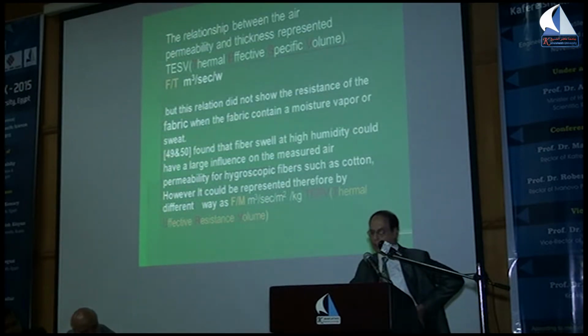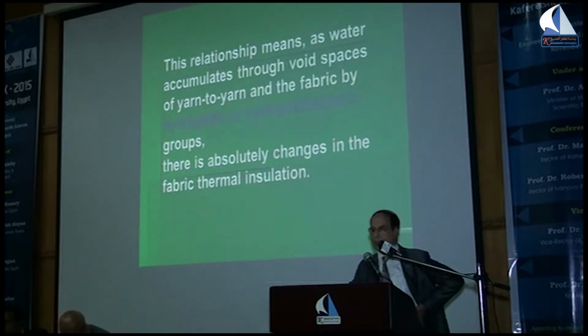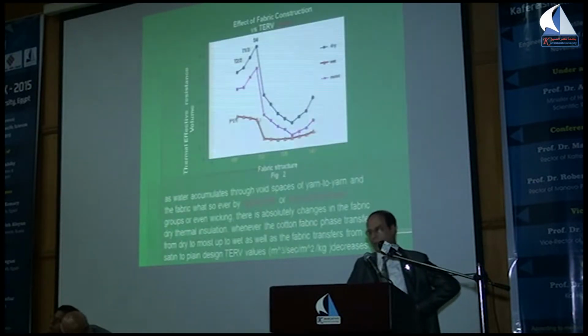So it could be represented in a different way, by the air permeability and the weight of the fabric. I called it the thermal effective resistance volume. This relationship means that as water accumulates through the void spaces between yarns and in the fabric, by hydrophilic or hydrophobic groups, there is an absolute change in the fabric thermal insulation.